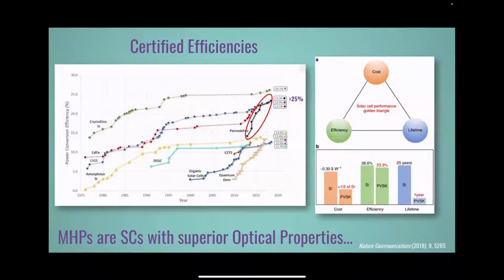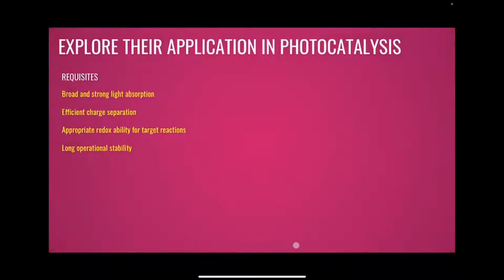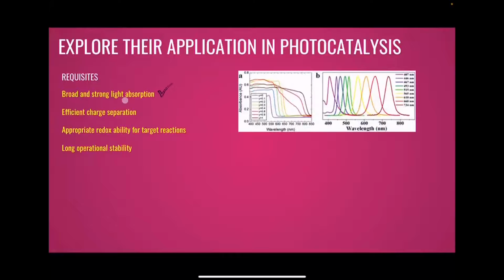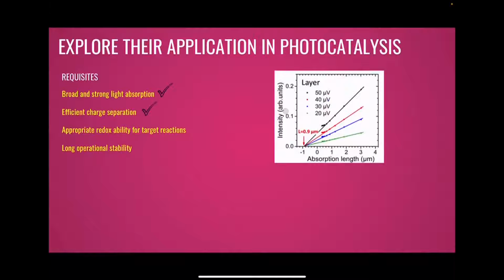However, our approach: we started in 2015 to investigate this material for optoelectronic and photovoltaics applications, but we thought a couple of years ago that, well, in the end, metal halide perovskites are semiconductors with superior optical properties, okay? So why not try to apply them in photocatalysis? Essentially, a good photocatalytic material should have a broad and strong light absorption, and perovskites have this. Here you see how you can easily tune the visible light absorption by changing, for example, composition. These are emission spectra. Of course, you also need for a good photocatalyst a very efficient charge separation to promote the redox reaction, and this is the case of metal halide perovskites.